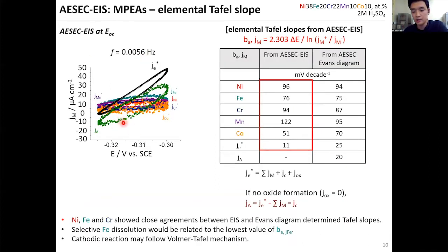So I just summed up the Lissajous plots of all the elements here, and I tried to calculate the Tafel slope using this elementally resolved Lissajous plot from the AESEC impedance. And as I previously showed you from the AESEC Evans diagram, I also calculated the elementally resolved Tafel slope. So at least nickel, iron, and chromium showed a really good correlation between these 2 different determinations of the elemental Tafel slope. Now, of course, there are some discrepancies, for instance for cobalt, which shows quite different values, which for now we think is due to the highly noisy signal of cobalt. It's kind of a technical artifact.